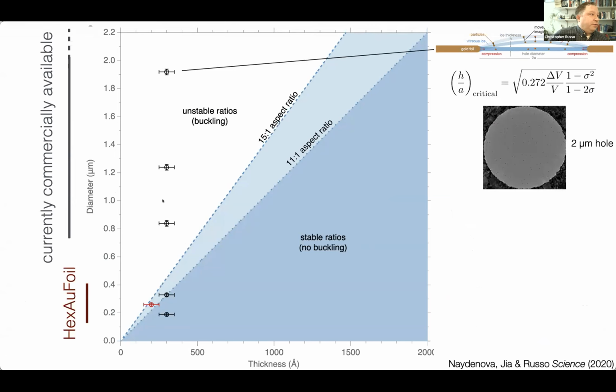And they are all in the regime where things are unstable because the specimen is only, say, 300 angstroms thick, but the hole size is much larger than 10 times that, right? And so only when you get down into this range do you actually end up in the regime where there is no buckling during the plunge. But this is where we wanted to be. So, but you could, of course, make a thicker layer of ice and then have stability even in a larger size hole. And we've seen that as well.